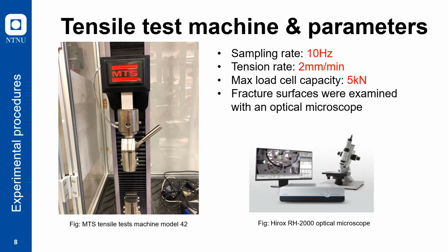So this is the tensile test machine and the parameters we used. We used the universal MTS tensile test machine. It has the maximum load cell capacity of 5 kilonewtons. And for the sampling rate, we chose 10 Hertz, which means 10 data points were recorded for each second. And for the tension rate, because PLA is sensitive to the tension speed, we chose 2 millimeters per minute in this case to avoid too fast or too slow conditions for the tensile test. And all the fracture surfaces were examined with an optical microscope after the test.